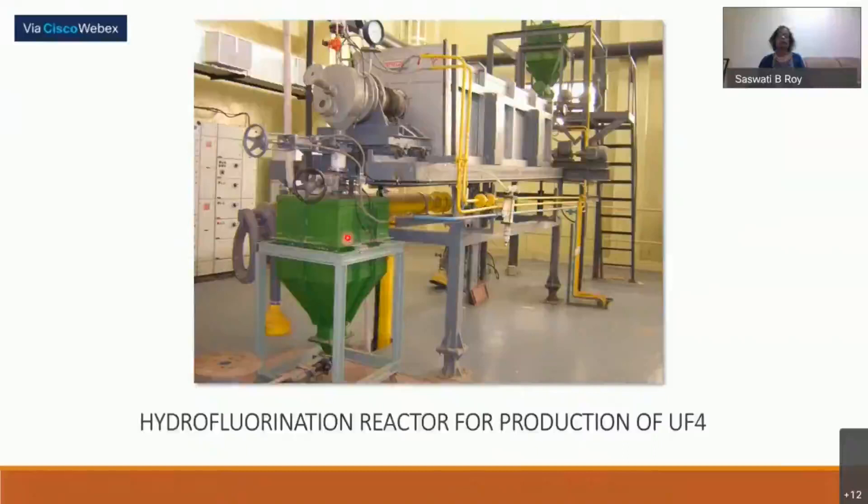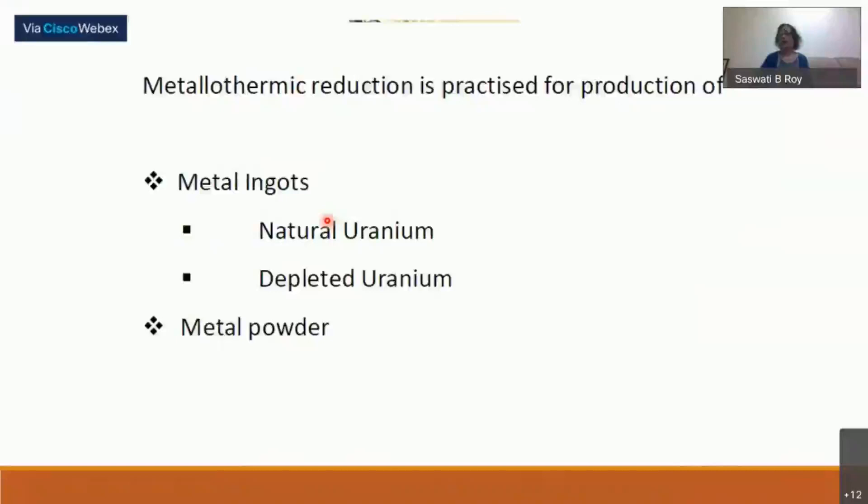Hydrofluorination is also done in similar rotary tubular horizontal furnace. Similar way of feeding and receiving material, and we have HF gas flowing counter current way. UO2 will get converted to UF4.